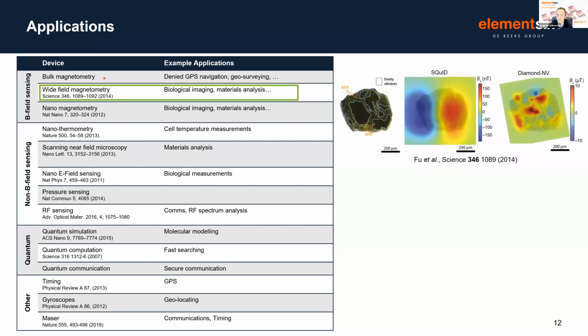So one is in the field of wide field magnetometry. So here, we're not only using the potentially high sensitivity of magnetic fields with NV centers, but we're also using the spatial resolution that an NV-based system can deliver. And this is a very nice paper from Roger Fu and collaborators at Harvard University, some of our collaborators, where they've taken a diamond-based NV microscope that they've developed with our material and imaged, believe it or not, meteorites. So really they're using this to probe the magnetic field signature of the early stages of our solar system.